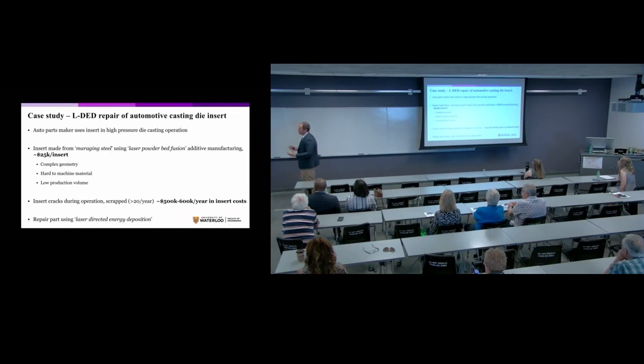So in this project that we're working on, we've been working on it for a few years, and this has a few more years left. But we're working with an auto parts supplier, a global tier 1 parts supplier. And they have a specific casting operation for aluminum casting. And in this casting operation, they put a piece of tooling into their mold, okay? And the tooling that they're using in this mold, it's very highly complex. It's made out of a very high strength tool steel. They produce very few number of these every year. So it's actually a prime candidate for the tooling itself to be printed. And it is printed by a technique called laser powder bed fusion.